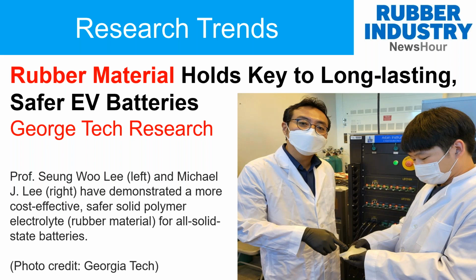These Georgia Tech engineers have solved common problems using rubber electrolytes. The key breakthrough was allowing the material to form a three-dimensional interconnected plastic crystal phase within the robust rubber matrix. This unique feature has resulted in high ionic conductivity, superior mechanical properties, and electrochemical stability.